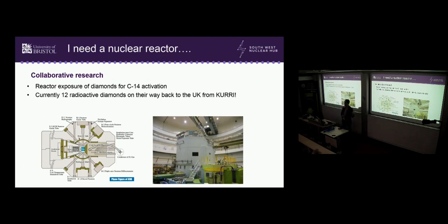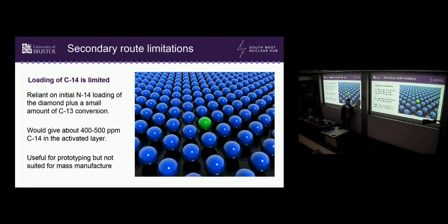We get this for free because we've got a nice strategic partnership with them. If I was to have to pay for this, I'd have to pay millions of pounds, literally £1 million a month, to run a nuclear reactor and get this. And what that does is it activates not all of the carbon into carbon-14, but enough that we can create a low-power device, something which probably gives something like about 10 microwatts.